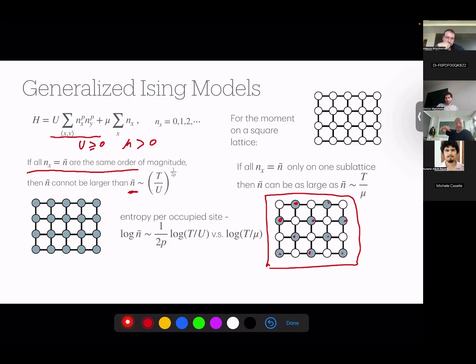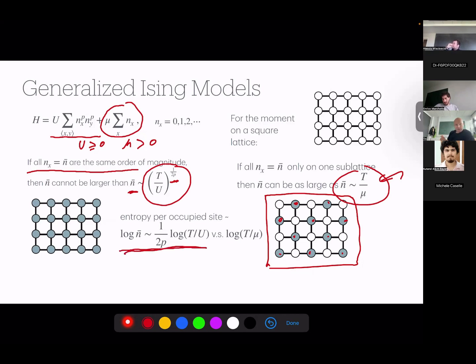But now notice one thing. Now these spins can take a much larger value because they are only suppressed linearly with n. Well, depending on p, of course. Depending on what p is, these spins can take a much larger or smaller value. In any case, it's a different scaling with t. Here we had the 2p-th root of t, and here we have scaling which is linear with t. So the point that I wanted to make is that the entropy per site, per occupied site, is very different. In the case of a gas, we have the entropy which is 1 over 2p times the log t. Whereas in the case of this, what I will call a solid, we have per occupied site that the entropy scales logarithmically with t, with the unit coefficient.